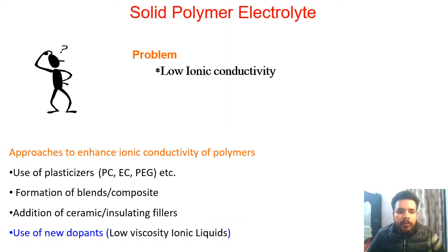In case of solid polymer electrolyte, the main problem is low ionic conductivity. They show very low ionic conductivity, which can be enhanced by the use of plasticizers, or you can form blends or composites, or you can add ceramics or insulating fillers, or there is another method that you can use: new dopants like low viscosity ionic liquid, which I have done in my present work.